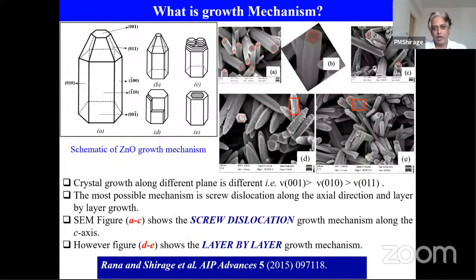Then I talked about the growth of the needles. Why is it forming the needle-like structure? The mechanism behind that is also important. What is the mechanism of growing this needle or rod-like structure? What we found is that when we prepare the material, most of the material is oriented along the 00L direction. Hope you are understanding this: 00L, the Miller indices, the planes along which the material is growing. So this is growing around the 001 direction. When we prepare the rod-like morphology, it grows by layer by layer deposition. That is what we found. And the needle-like structure grows by screw dislocation.